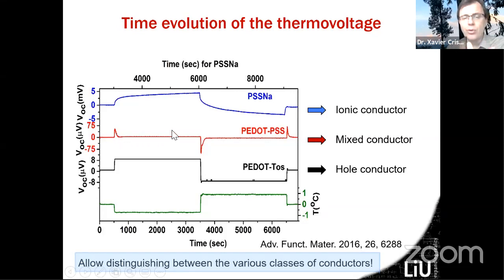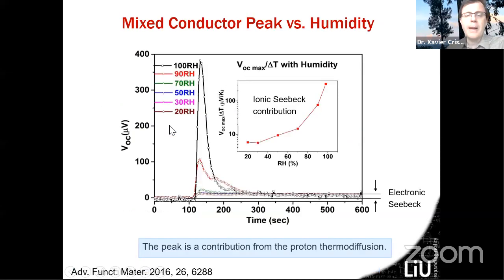And if we look a little bit closer, we can zoom in and vary the humidity. So what we discover is that if you look at the open circuit voltage and you apply the temperature gradient, at more or less 100 seconds here, you apply the temperature gradient, and then you see that the potential is increased.